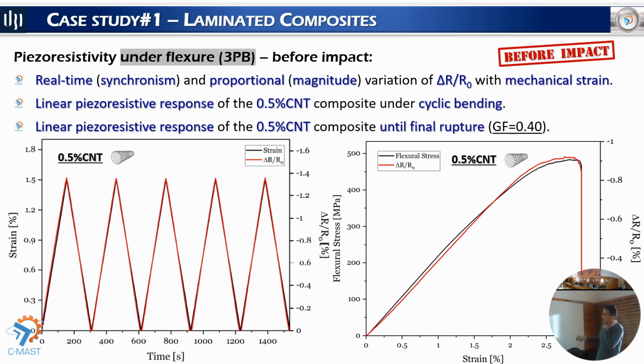We can see that when we apply stress, the electrical resistance of the material increases, and when we reach the limit, the maximum stress that the sample supports, we can see the appearance of some noise in the electrical signal, which means that some permanent defects are being imposed on the sample, and this is exactly what we want to achieve. A good correlation between the mechanical part and the electrical part, and if we measure the electrical signal variations in real time, we can have an idea about the integrity of the sample.